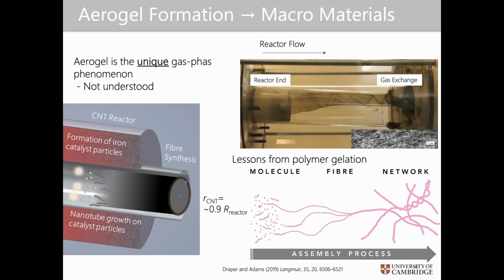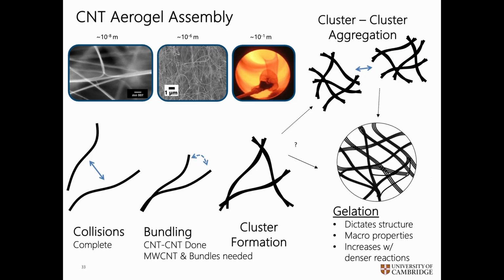And you can think that polymer science kind of did this a few decades ago, right? Polymer physicists were looking at these types of processes where you get monomers ultimately polymerizing and then assembling into materials. And we can think of analogous processes in the gas phase. So the first thing is we have collisions between nanotubes, and that's Brownian motion walking these materials around. They collide with one another, and they have an incredible amount of surface energy. And that surface energy, if given the chance, wants to be lowered, right? So they would prefer to be in bundles if their energetic preference were allowed. But what happens is they bundle up to a point, and then you start getting cluster formation.